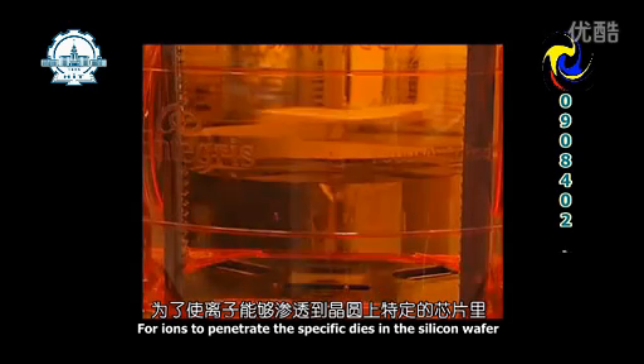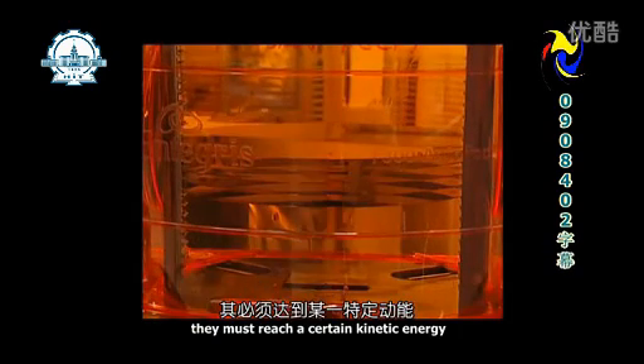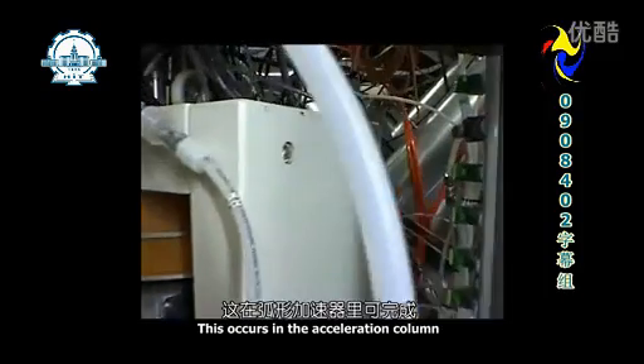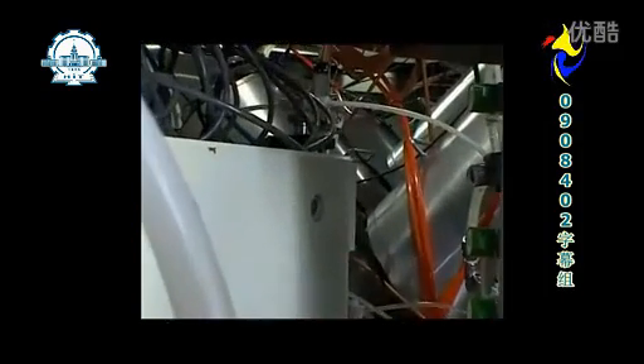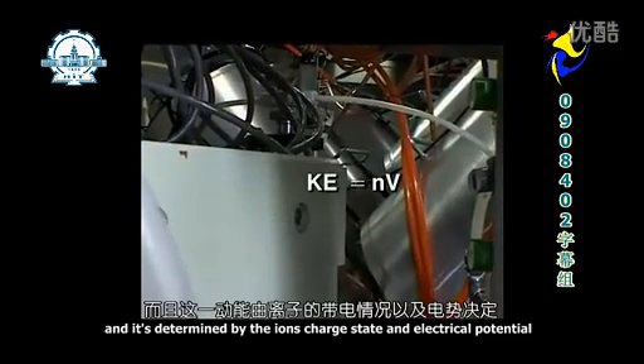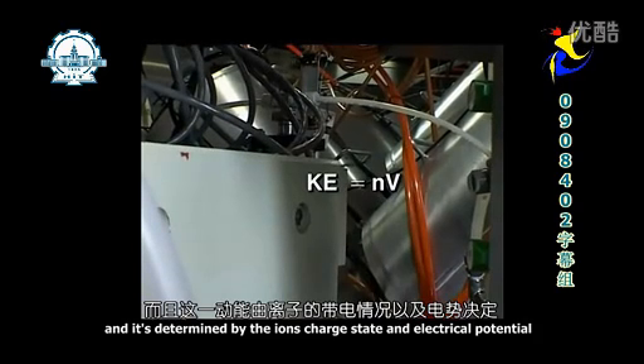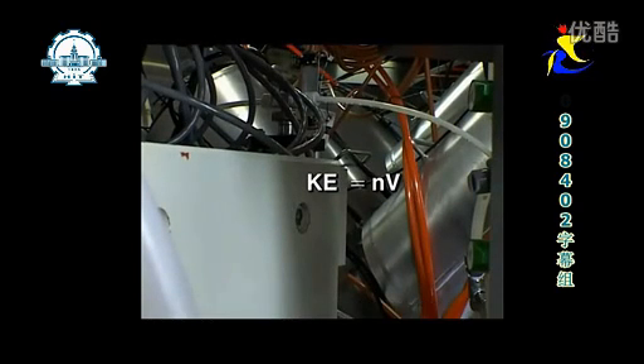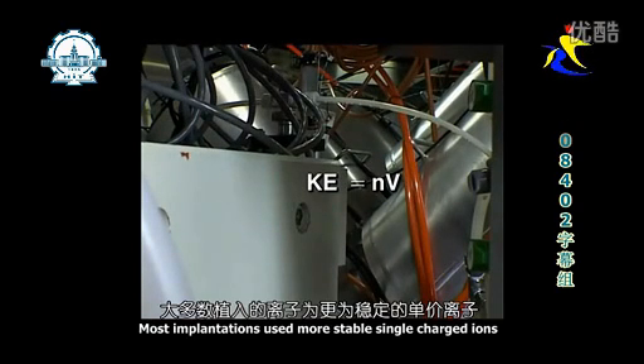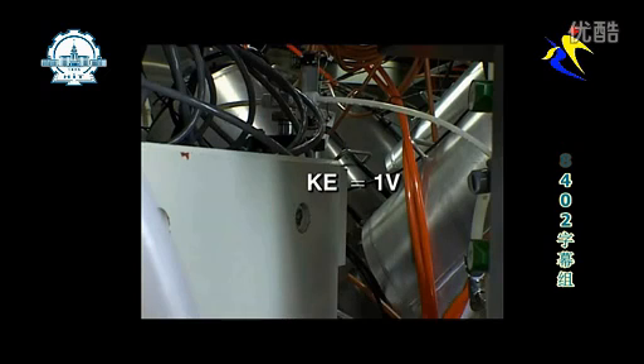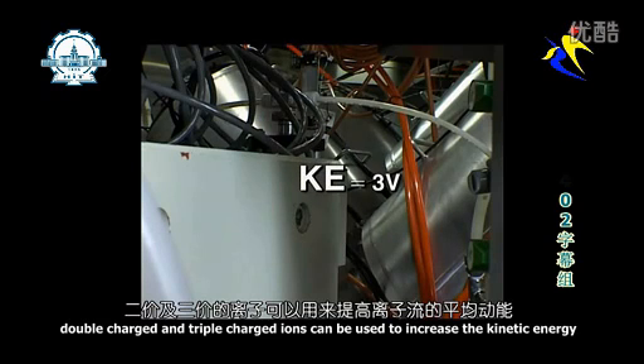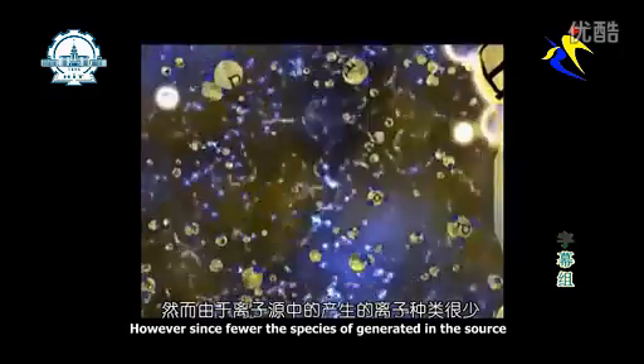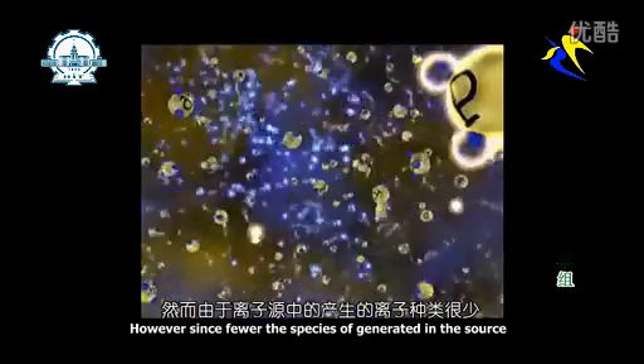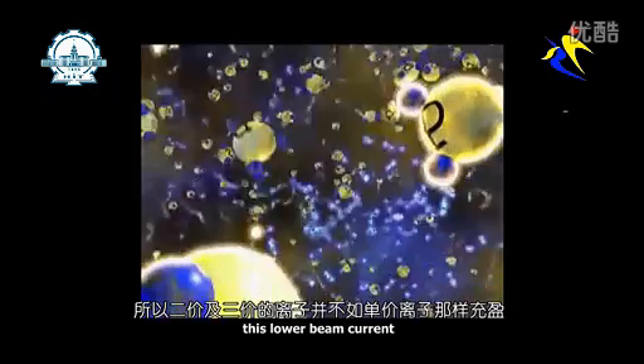For ions to penetrate a specific depth in the silicon wafer, they must reach a certain kinetic energy. This occurs in the acceleration column and is determined by the ion charge state and the electrical potential. Most implantations use the more stable single-charged ions. Double-charged and triple-charged ions can be used to increase the kinetic energy. However, since fewer of these species are generated in the source, this lowers the beam current.